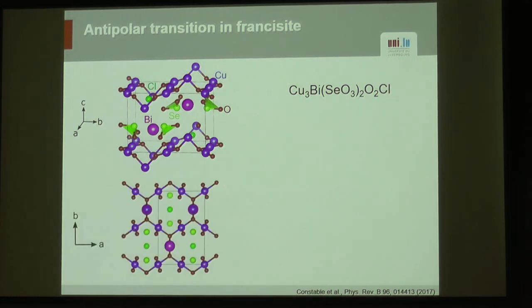When you look at it from the top, so along the c-axis, you see that it realizes this kind of hexagonal Kagome lattice, and this is the reason why this family has been investigated so far. It's because from this kind of lattice, you will find intrinsic magnetic frustration and mechanisms. So this is the reasons why people have been looking into those materials.